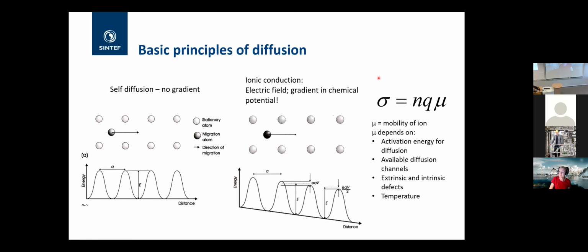Here is the basic equation for conductivity, and the n here is just the number of charge carriers, and the q is the charge, and then you have mu, which is the mobility of the ion. The mobility will depend on the activation energy for diffusion. In many cathode materials, this one is relatively high, meaning it's around 0.4 to 0.6 electron volts. Also, the available diffusion channels, which I've shown in these different structures.